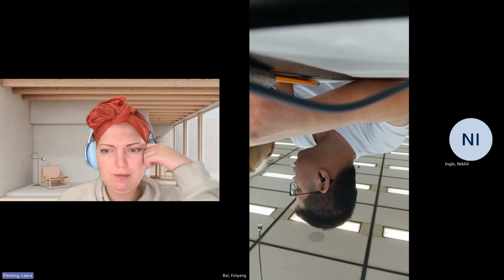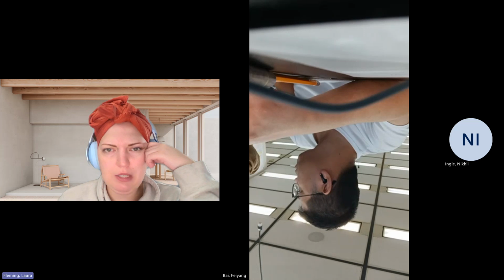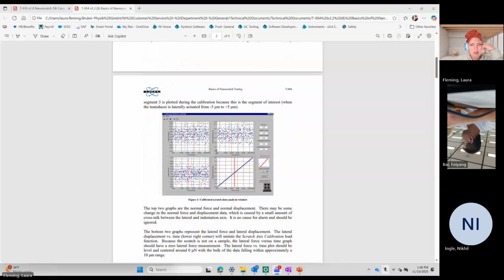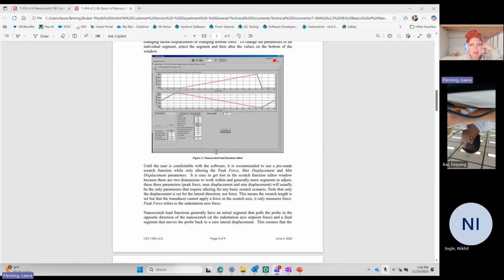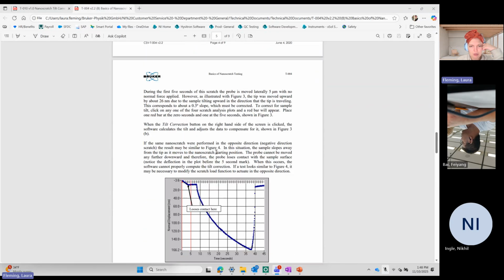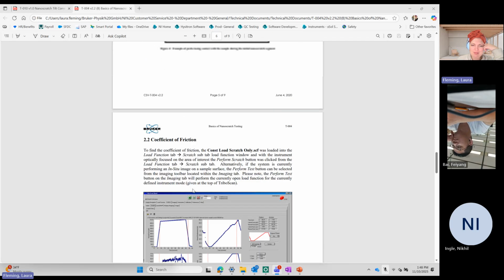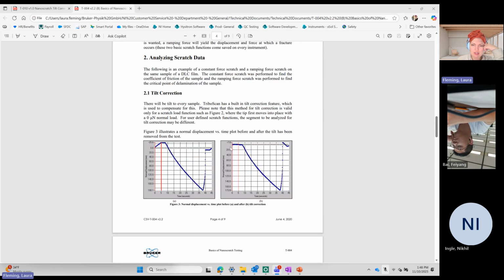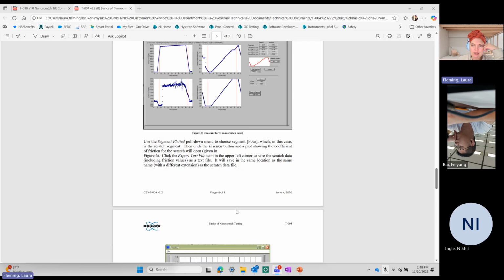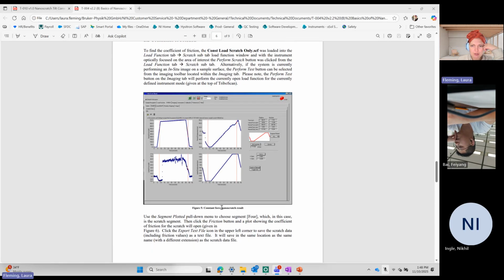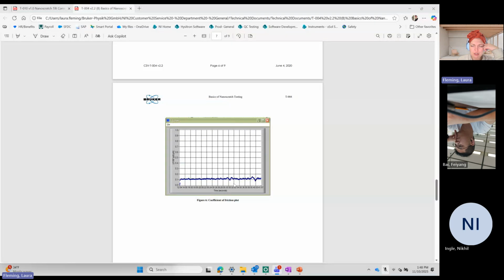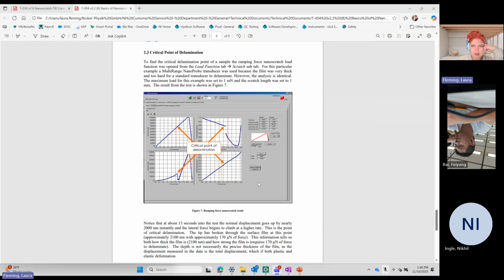Let me reshare here. I think you might have a slightly updated version of this, but. So there's this basic nano scratch testing, setting up a scratch, goes through the tilt correction. This one's a little bit more obvious because there's not so much strangeness. So here you can see between here and here, it's flat before and after. But if we're looking at data, this is a coefficient of friction result, in which case you can get this friction plot. So that's some analysis you can do.